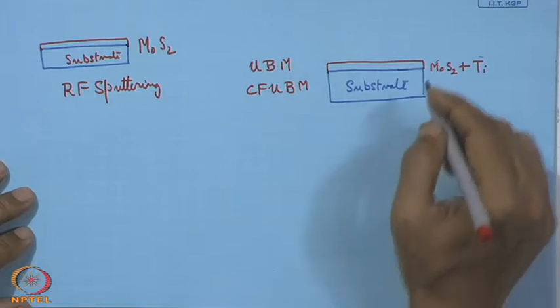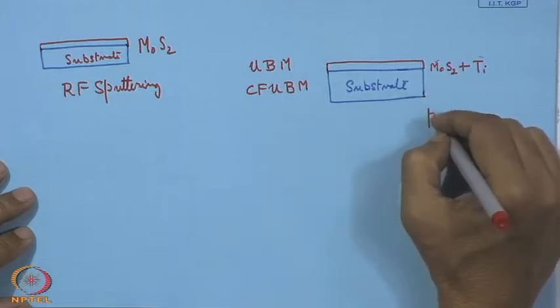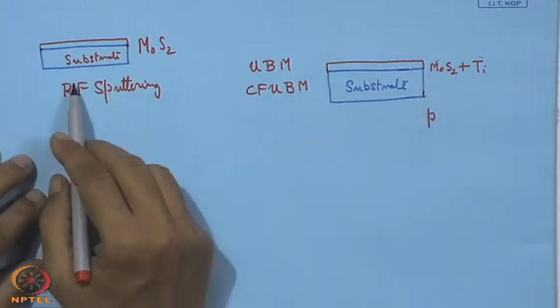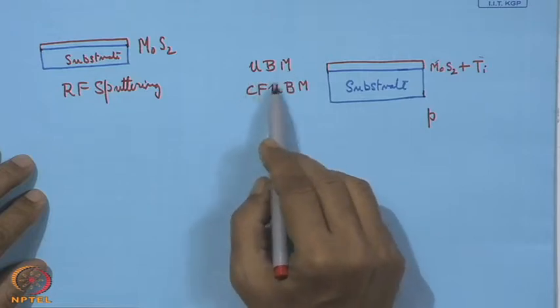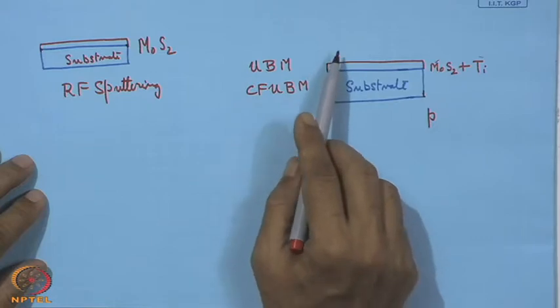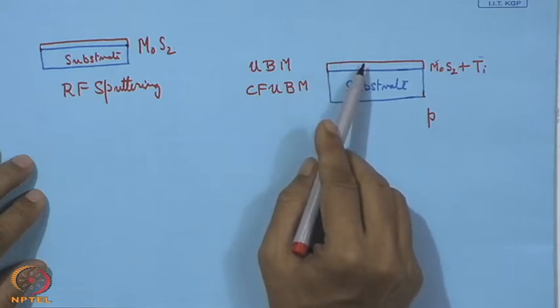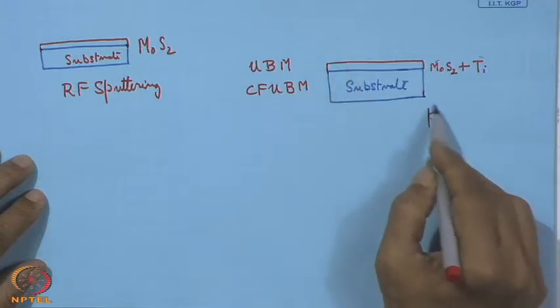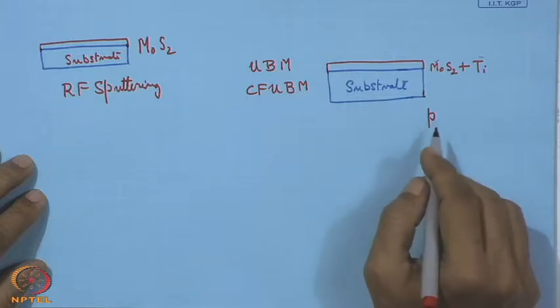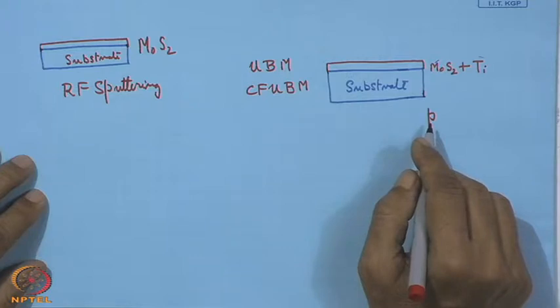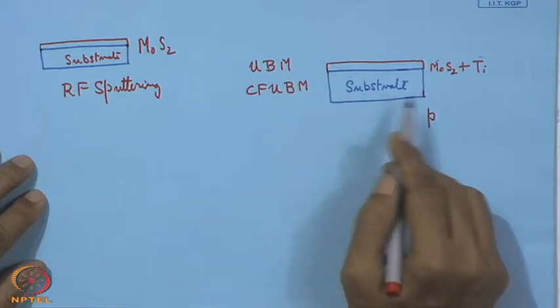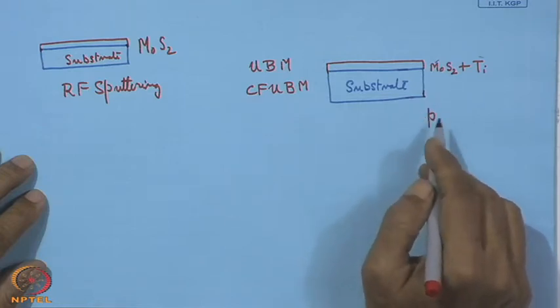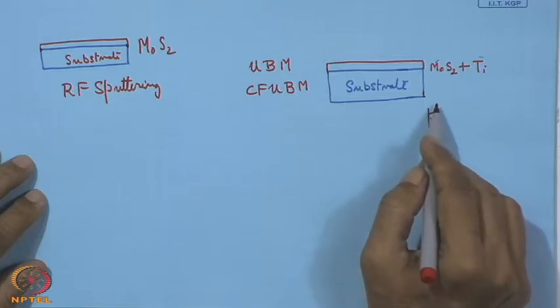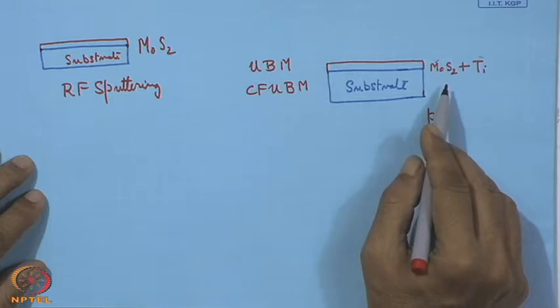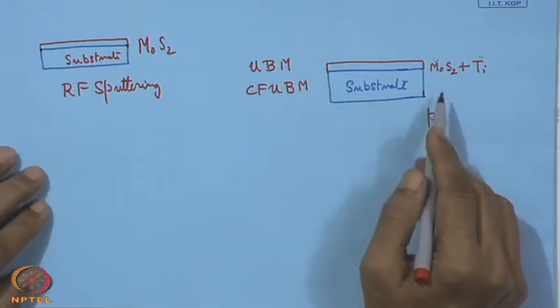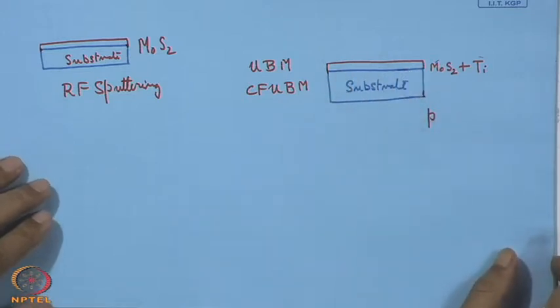Here also the process pressure can be brought down compared to what is needed here, because it is now unbalanced magnetron or closed field unbalanced magnetron. So, with that we can bring high ion current on this side, and that is actually the case where we can work with still low value of the pressure. And according to this new structural diagram for this coating architecture, we can see that even with low pressure and low temperature, we can get a very good architecture of this coating. And then we have widened the scope of activity of this coating.